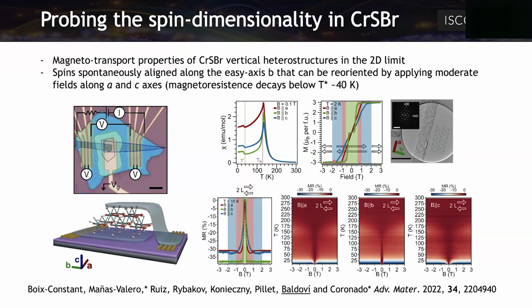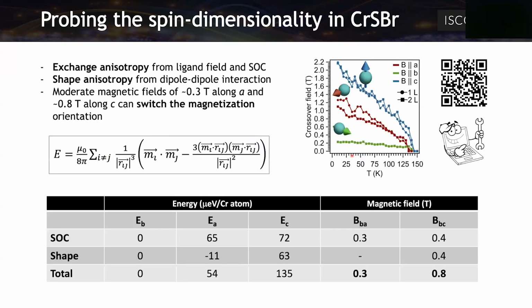So it was possible to change this, and they were checking it with magnetotransport properties. And we were doing the calculation to see if we can make a prediction of how easy it will be in a perfect material. Of course, we are considering a perfect 2D material. We are not considering all the bias, but we observed adding dipolar interactions, not only the effect of the spin-orbit